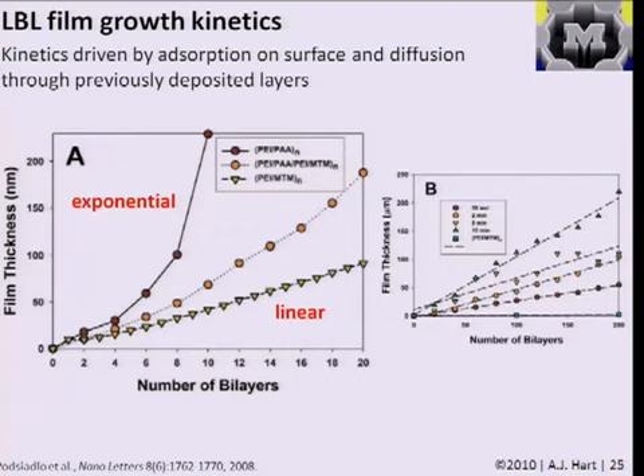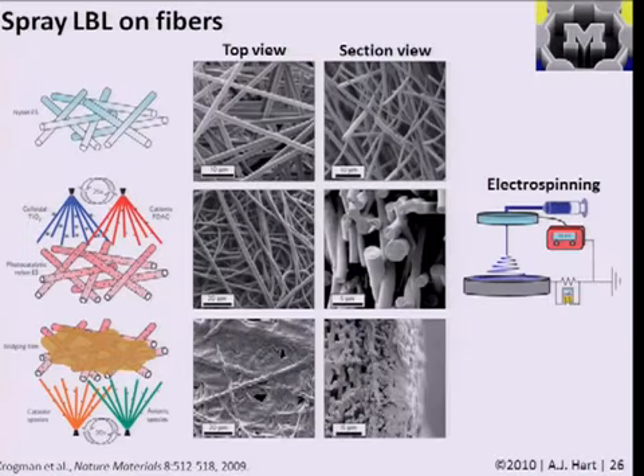So this might straighten out to a line of slope like this, and this case might stay at a lower slope like this. Different polymers and different components determine whether one kinetic happens or another because of how well they organize and how well one molecule might diffuse into another. And indeed, this study found that even though you had these clay sheets, which you could imagine are blocking the diffusion of molecules into the pre-existing film, the polymers, because of the strength of their interactions, were actually able to snake their way down into the pre-existing layers, and that growth mode existed in this material.